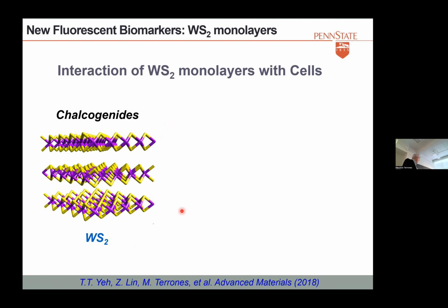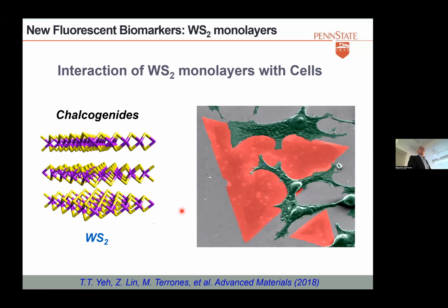So they are fluorescent, so they can be used as biomarkers, right? What happens is if a cell ingests this, they can start fluorescing, and they can monitor where the cells are. This is similar to a fluorescent biomarker. So what we did is we used the tungsten disulfide. We have these cancer cells, and what was surprising is that when you put a cancer cell on top of this material, the cells start digesting the material, and they start fluorescing.